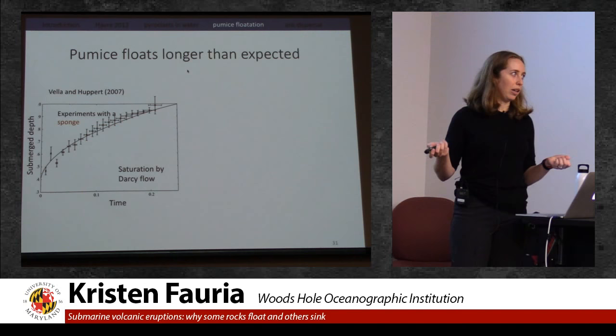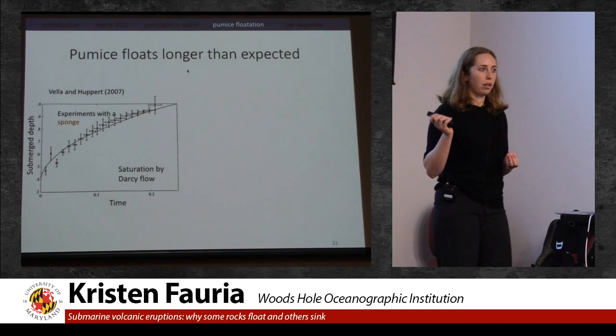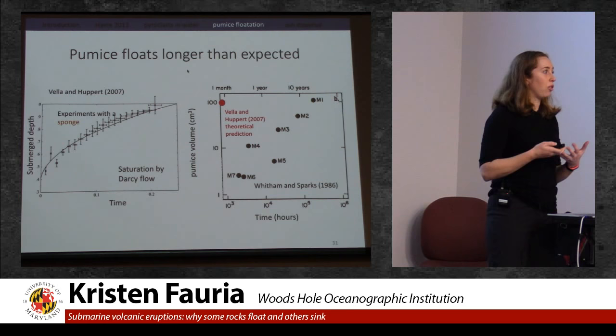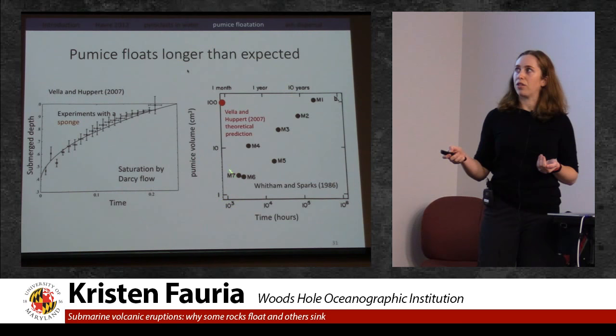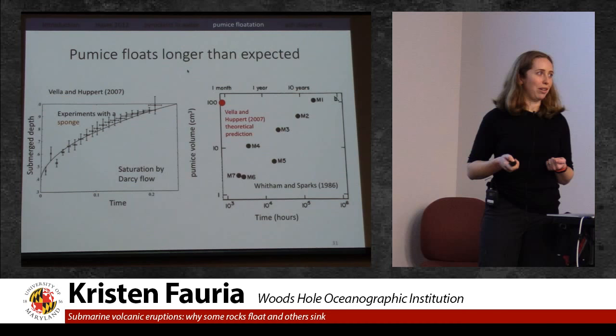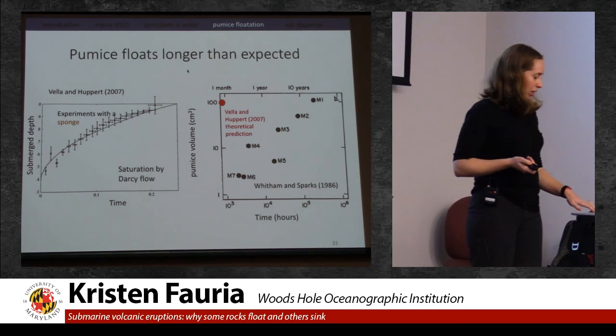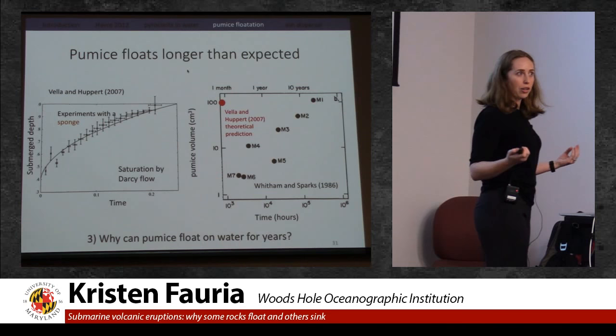But if you compare this model for the saturation of porous media to observations from pumice, you see that pumice actually floats much longer than predicted. This is the time versus the size, and this porous media saturation model is here, and we're off by several orders of magnitude. So this really raises the question: if pumice pores are mostly all connected, and water wets volcanic glass, why is it that pumice is able to float for so long at all?